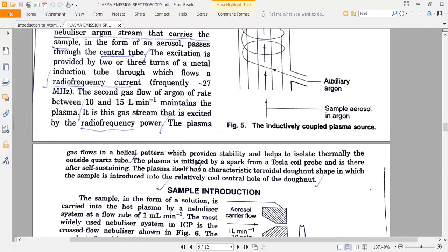The plasma is initiated by a spark from a Tesla coil probe and is thereafter self-sustaining. The plasma itself has a characteristic toroidal donut shape in which the sample is introduced into the relatively cool central hole of the donut.